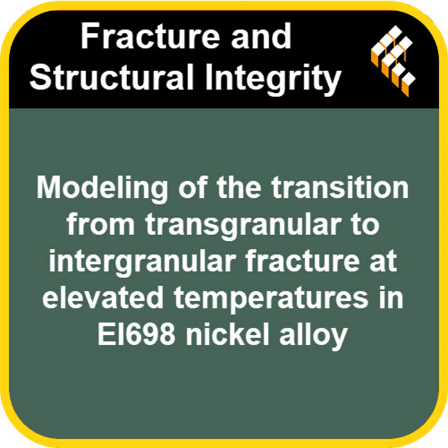Exactly. And the core mechanics of this phase field model are, well, quite elegant, as you said. It's based on a fundamental concept in fracture mechanics called Griffith's balance, that looks at the energy needed to create new crack surfaces. But the key addition here is accounting for that non-local region of damaged material we talked about. It captures the idea that a fracture isn't just a single point failing. Okay. And for practical implementation, they actually created a new custom element for ANSYS software, the big engineering simulation package. They used its user-programmable features, which is pretty significant because it means this powerful phase field approach can work seamlessly with basically any nonlinear material model that engineers might already be using in ANSYS. That's huge for usability. Absolutely.